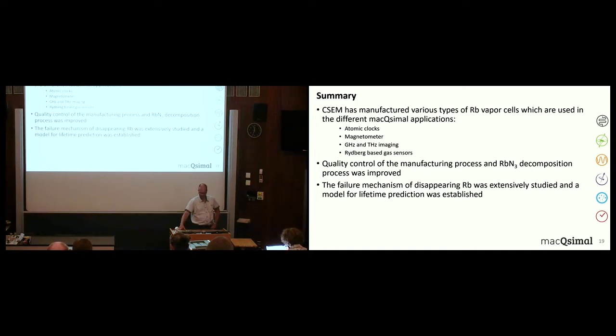We made a huge progress in the quality control of the whole manufacturing process, and in particular in the decomposition process of the rubidium azide. The control of quantity was improved, and we have made extensive studies on the failure mechanism of the disappearing rubidium. So we were able to establish a model for the lifetime prediction.